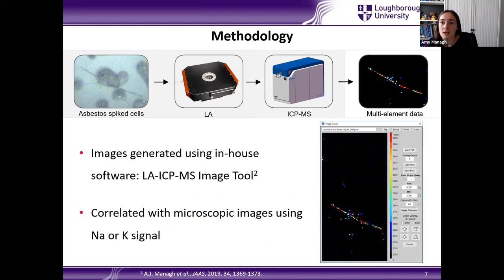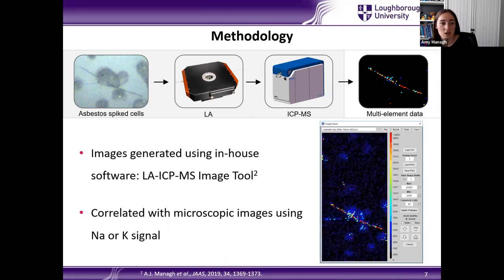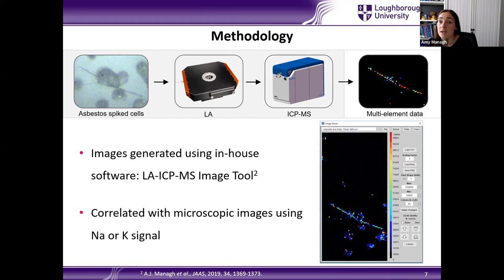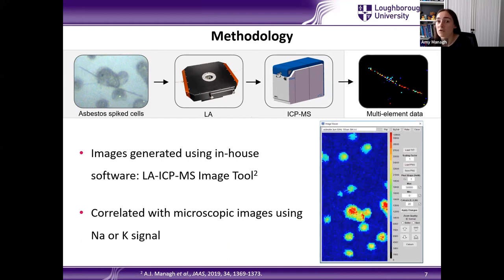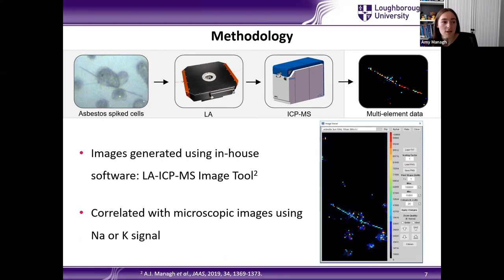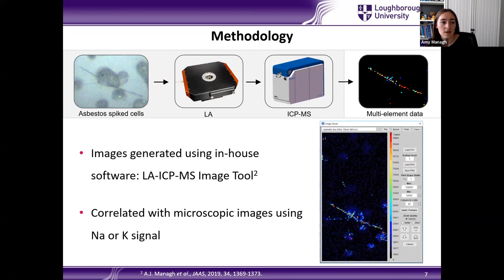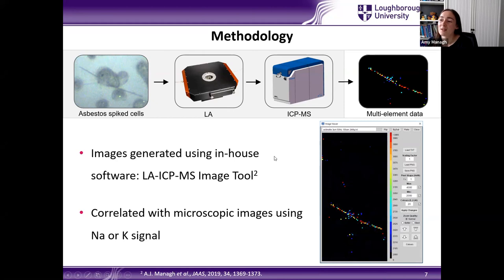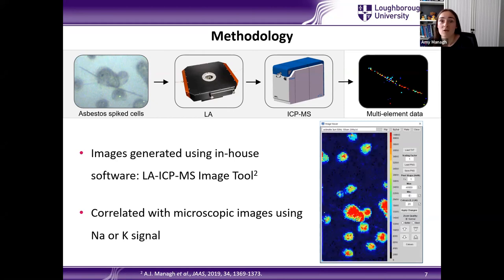The data from the TOF can be outputted to a variety of different software packages. For this work, we actually used some in-house software that we developed at Loughborough, the LAICPMS image tool. And this program is freely available to anyone that wants it. So if anyone's interested in the processing, please do get in touch and I can give you a link to where you can download that. We were able to correlate our ICP-MS images to our microscopic images using endogenous elements that are present within the cells. So for example, sodium here, you can see that our cells contain large amounts of sodium. So we're able to use that to overlay onto our microscopic images and see where everything is within the sample.